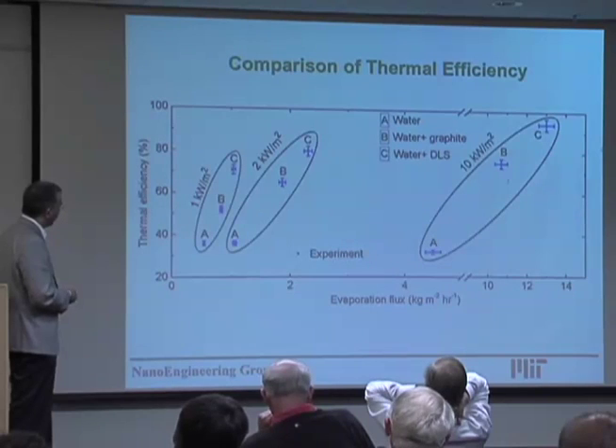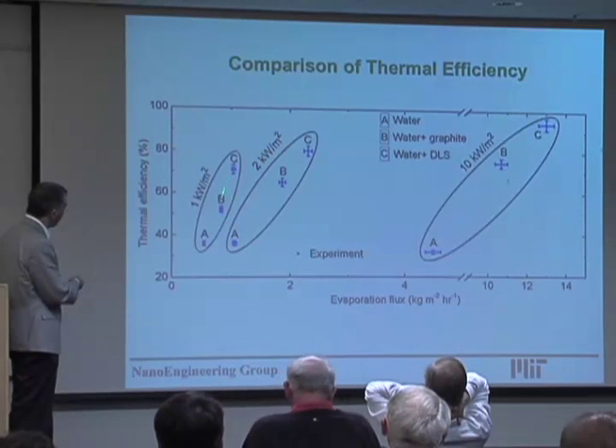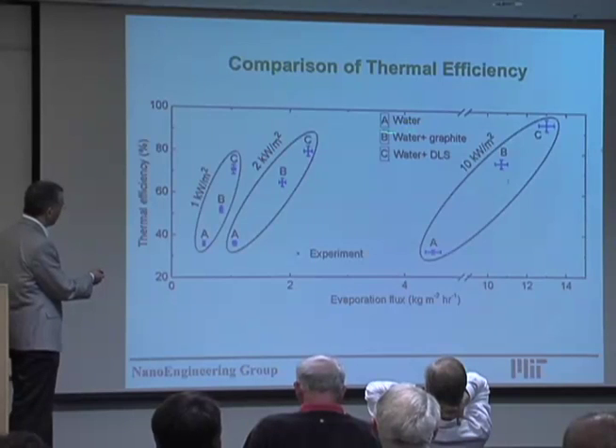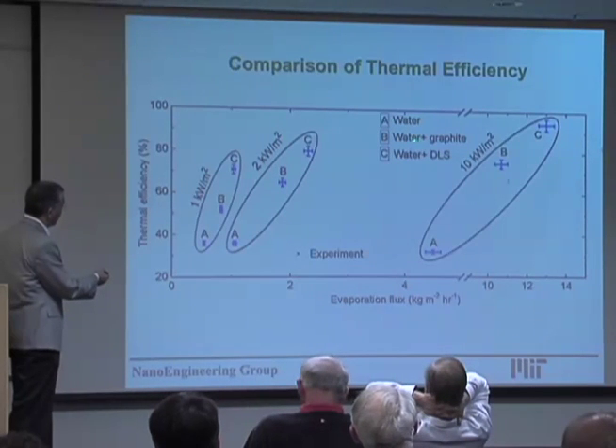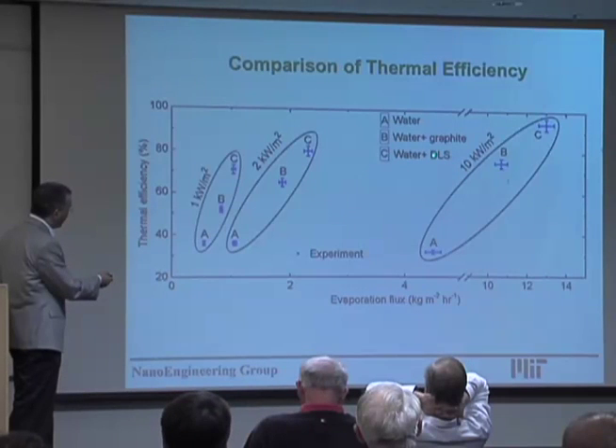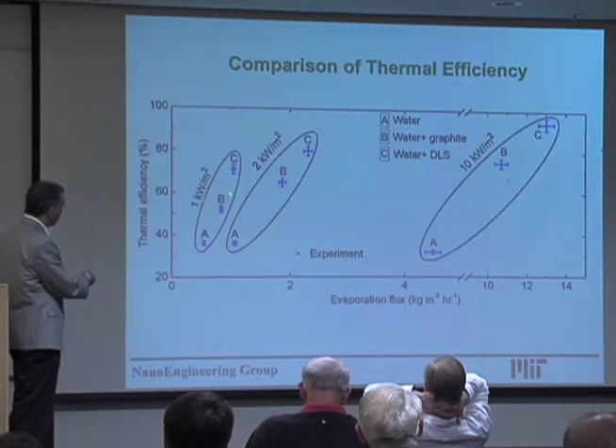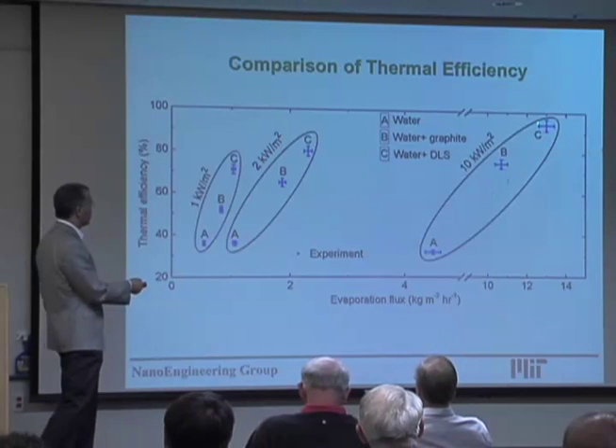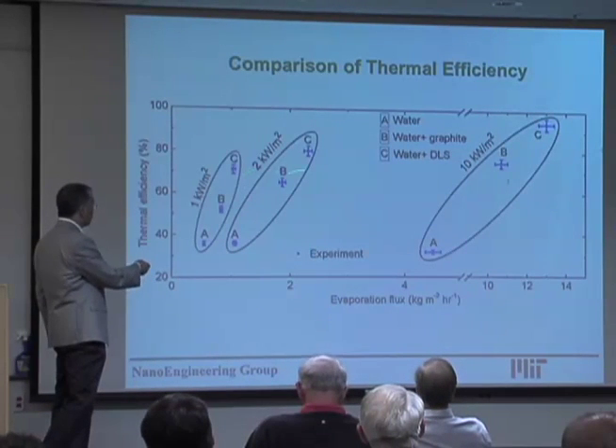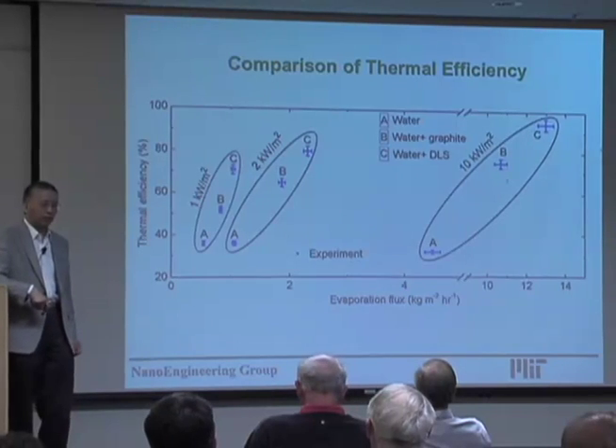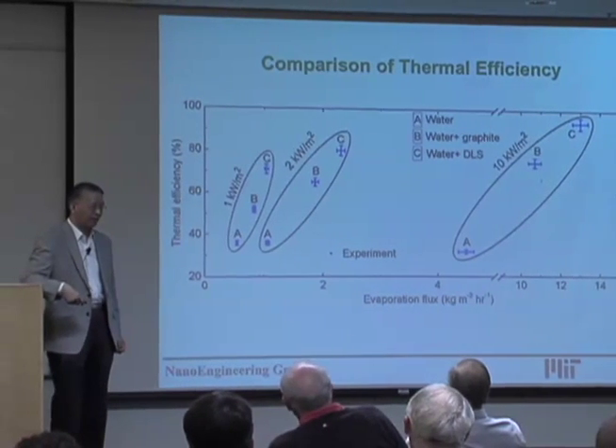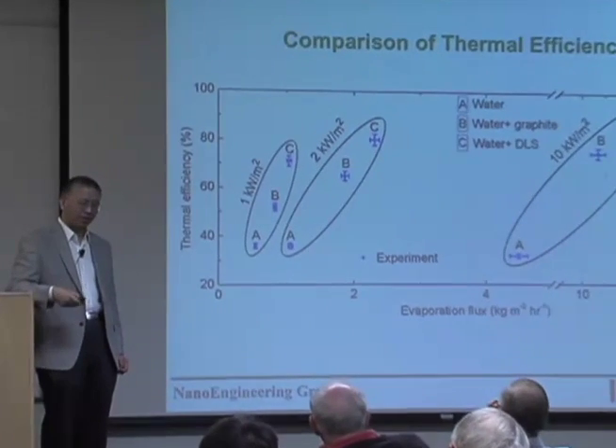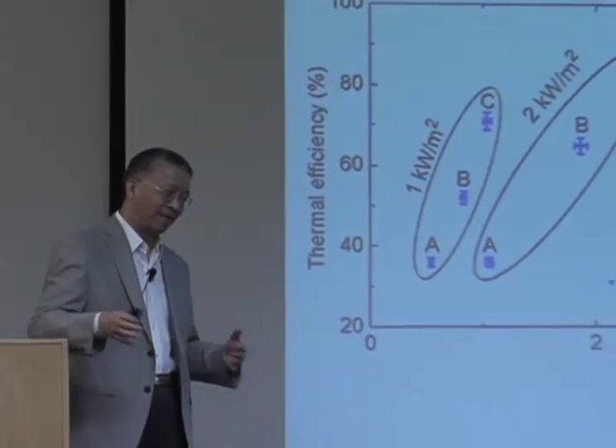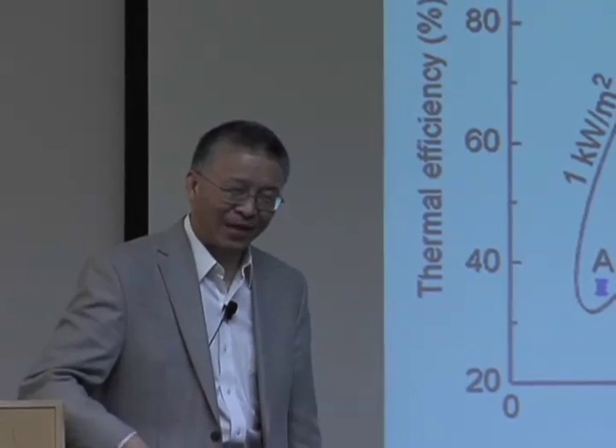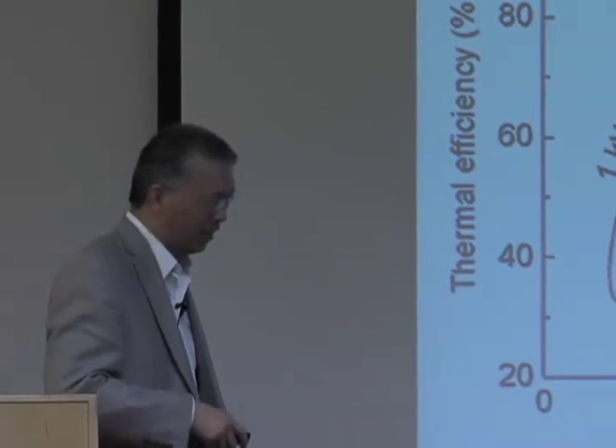And in terms of the efficiency, we compare different cases. This is just shining light directly on water, shining light on water with graphite, or with this double layer structure. And you can see the efficiency, this is the 1 sun, 2 sun, and 10 sun condition. And we get a pretty effective water evaporation. So we're actually working a lot. This is beyond what we're doing in solid state. Now we're actually getting also back into my mechanical engineering roots, looking into those phase change materials.